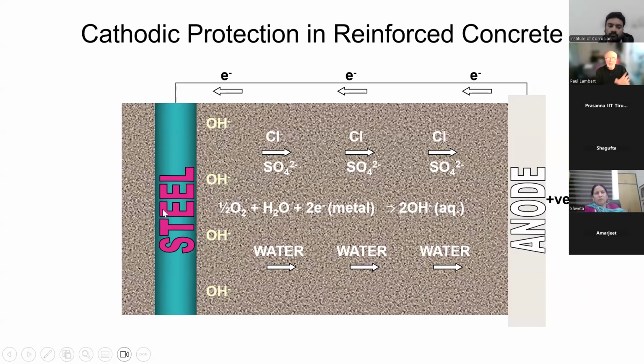So that environment, that annulus around the steel, very quickly becomes high in alkali, low in chlorides, low in water. Good conditions to maintain not only no corrosion now, but no corrosion if the system goes off for a while. So with steel and concrete, if the system goes down for a few months, frankly, it doesn't matter. It's not a matter of sending out a motorcyclist with the spare parts to repair and make sure it's working again. It's more a case of remembering to do something about it the next time you're out there. Be it 6 months or a year later, it probably doesn't matter once it's been operating for a while. As I say, it works incredibly well.